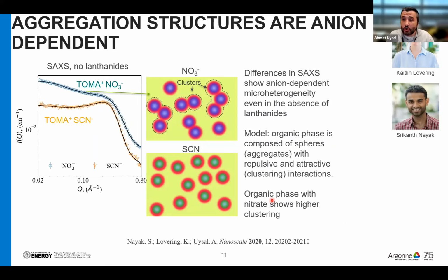Nitrate and thiocyanate show very different structuring in the organic phase. Thiocyanate likes to form these aggregates that behave like hard spheres. When I say an aggregate, these are my extractants forming a structure with their tails out and their heads at the center. So the hydrophilic centers and hydrophobic tails in the oil. And they act like hard spheres. So we see the structures, we can model them as spheres in our small angle X-ray scattering data.